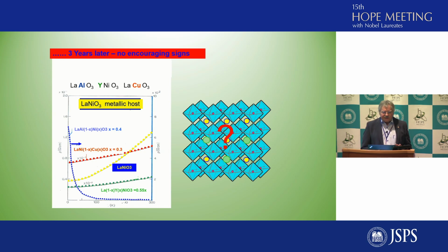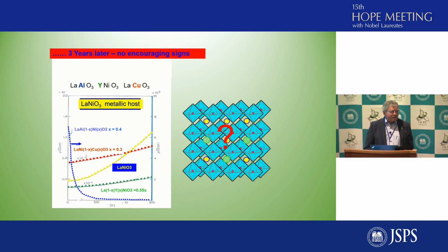3 years later, after our start, there were still no encouraging signs that we would ever end up with a superconducting oxide at a reasonably high temperature. So what we did is we partially replaced ions in the center of the octahedra, sometimes in the center of the unit cell, and the corresponding results in resistivity as a function of temperature. We see here that was our host material, the material we started with, and then did some variations. We were replacing the A site, keeping the nickel site untouched. We were replacing the B site, changing the ratio nickel to copper on the B side.